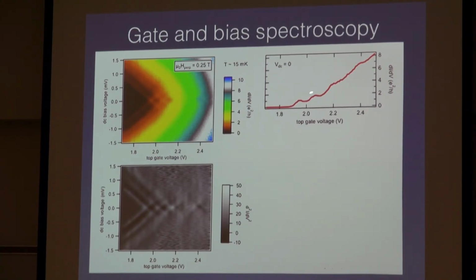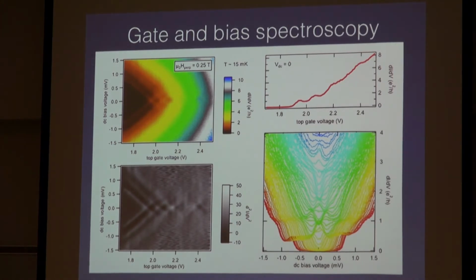There's something funky going on here. And I would say when we first saw this, we were like, you get wiggles in conductance all the time. The fact that they happen to be around 1 and 2 e²/h is nothing exciting. But when you start to look at the bias spectroscopy, the voltage bias spectroscopy, in addition, so this is the DC, so this is basically slices of this thing as you approach this turn-on point.